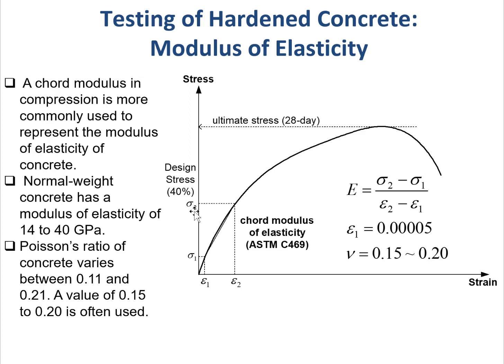Sigma 2 is the design stress, which is 40% of the ultimate stress. Remember that ultimate stress is the peak load on this curve, and then you can calculate the design stress, and the strain epsilon 2 is the strain corresponding to this stress level. Okay, so after you locate these 2 points, then you can calculate the chord modulus E, which is equal to sigma 2 minus sigma 1 over epsilon 2 minus epsilon 1.